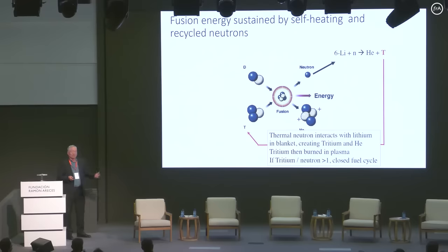This is the lighter form of natural lithium. This produces another helium particle and a tritium, which is the heaviest form of hydrogen. Because tritium does not occur naturally, you take this tritium and put it back immediately into the system and reburn it. This is very important because it means we must get a tritium per neutron greater than one, which means we're creating our own fuel to sustain this.